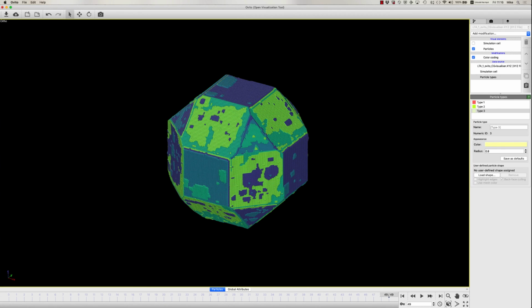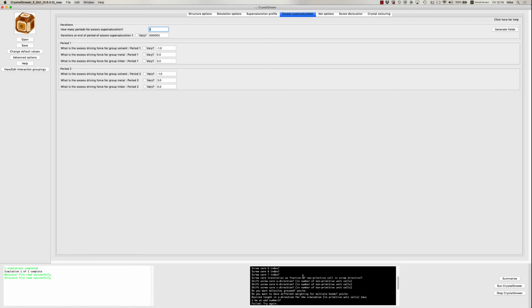So the different facets have different thresholds above which you need to get in terms of supersaturation for them to nucleate and then begin to grow, and this will ultimately be reflected in the overall morphology of the crystal at different supersaturations. The last type of structure, which is slightly different and needs to be treated in a different manner, is a metal organic framework, a MOF.